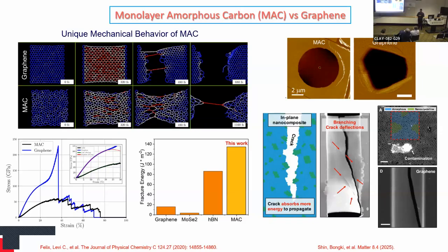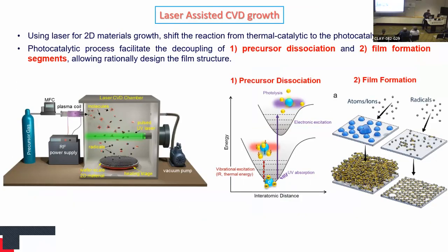That is the main point. Yeah, that's exactly right. There are a few papers in the previous studies also. There is always amorphous carbon there, and people wanted to get rid of that to have a single crystalline layer. Even for this work, our aim was to grow graphene, but we ended up growing amorphous graphene. That becomes very useful in the end. So that was the trick behind that growth.